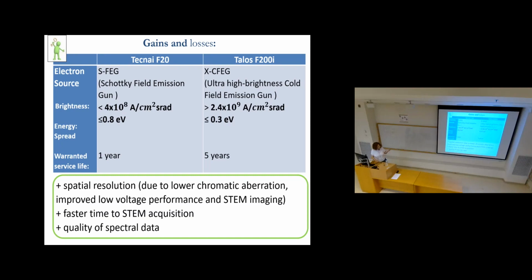Of course, it helps to make the STEM acquisition, the scanning transmission electron microscopy, faster, easier, and provides higher resolution. And also the quality of spectral data should be much higher with the Talos because we have more electrons per unit area. So we excite with a denser flux, and we can get a higher flux of X-rays, for example, and we will see it.